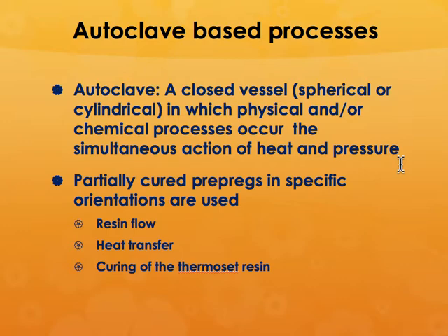But of course, the pressure used is only between 100 to 125 psi, but typical vessels can be as big as 20 feet in diameter by about 100 to 150 feet in length, which means that it applies considerable pressure over the entire component, and it's an expensive process.